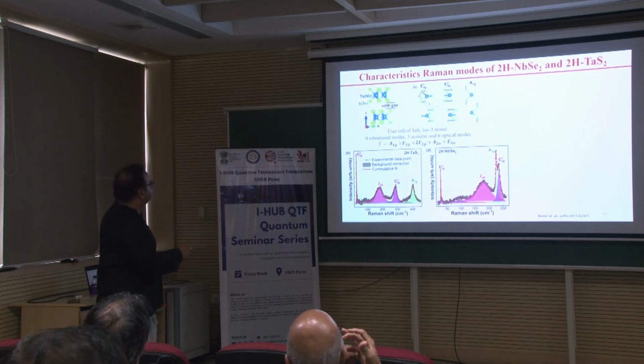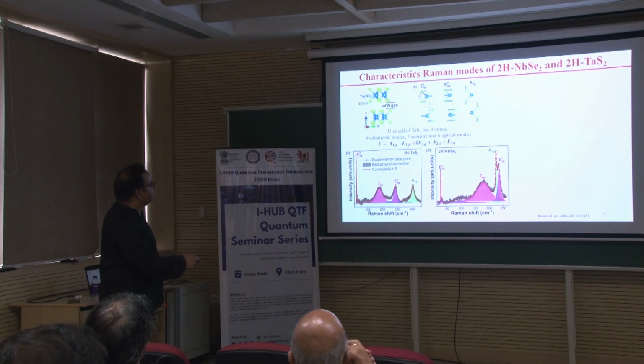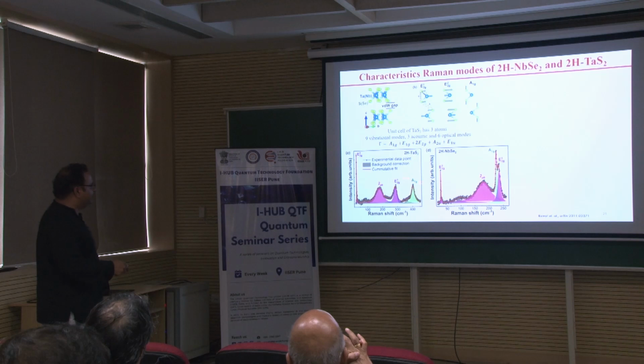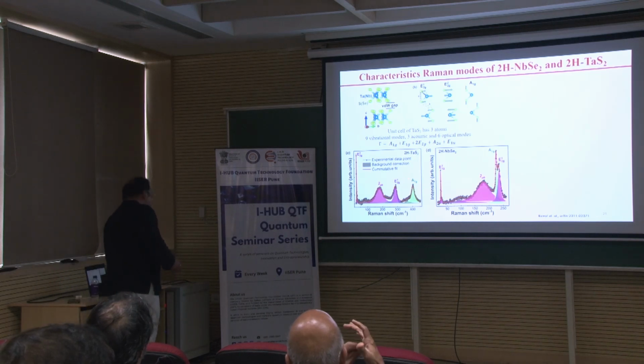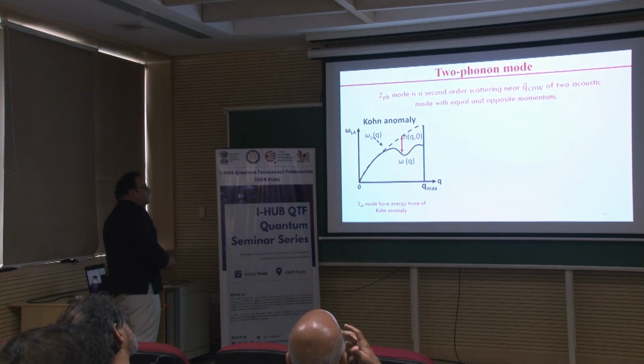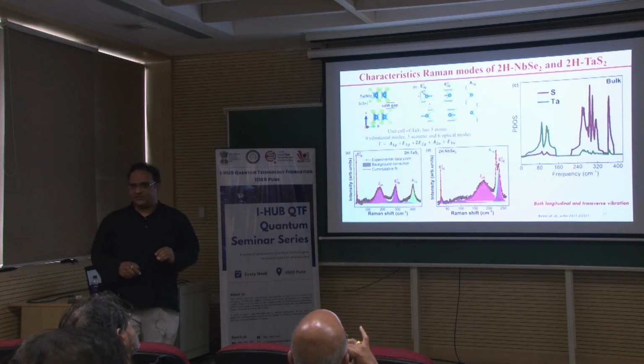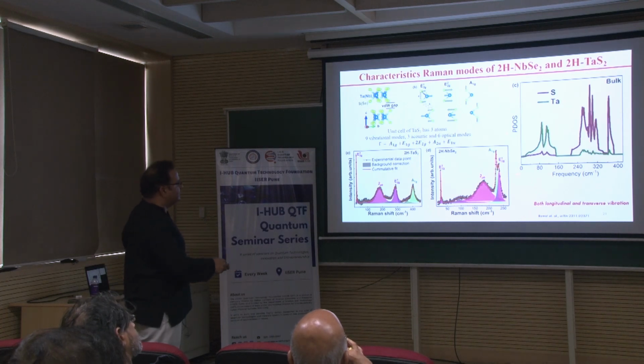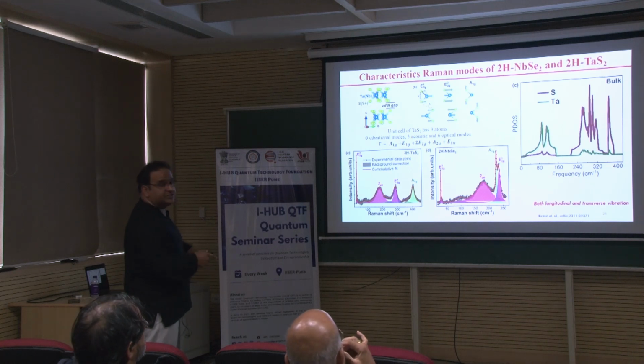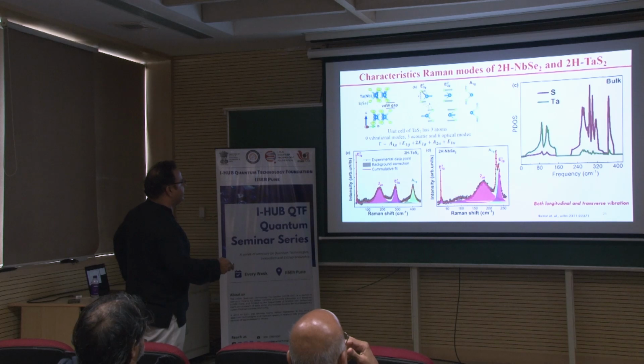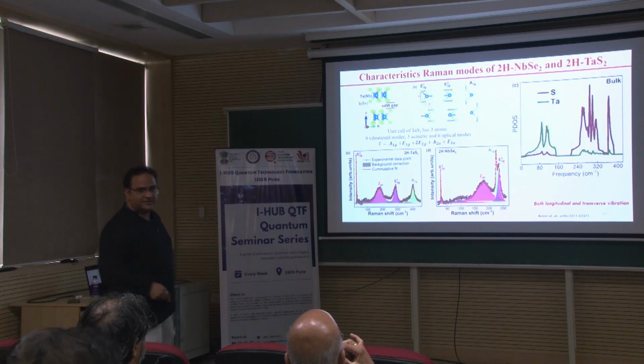All right, because niobium selenide or tantalum sulfide have 3 atoms per primitive cell, you expect 9 vibrational modes, out of which 3 will be acoustic and 6 will be optical, but not every one will be seen in Raman spectra. The interesting aspect here is the phonon density of states, frequency versus PDOS. This is tantalum sulfide. Until 140 you have modes primarily from the vibration of the tantalum atom, because it is heavier, so low frequency vibrations are dominated by tantalum. The high frequency will be dominated by sulfur, and there is a gap here in the phonon density.